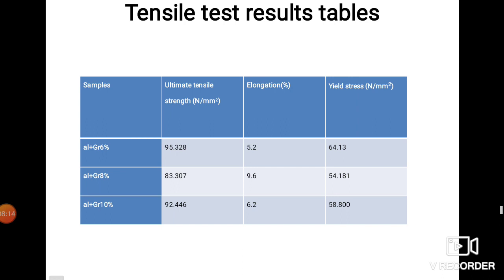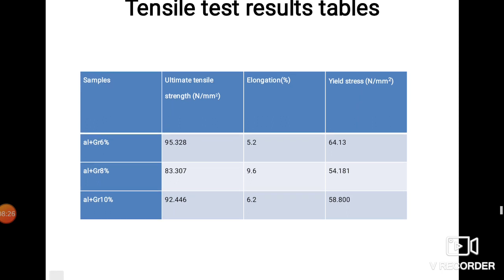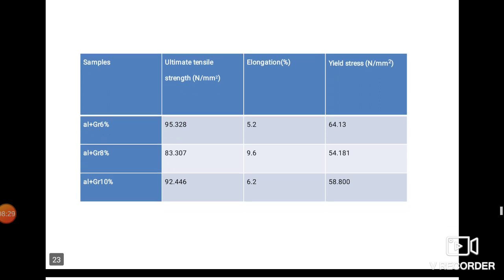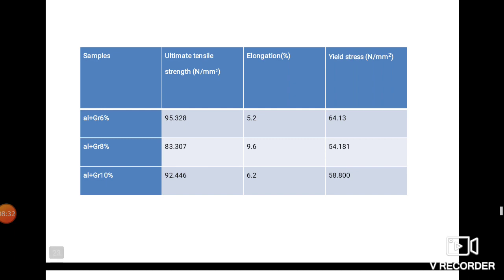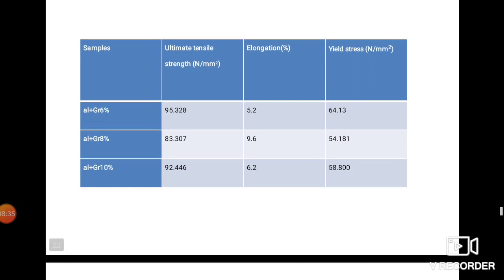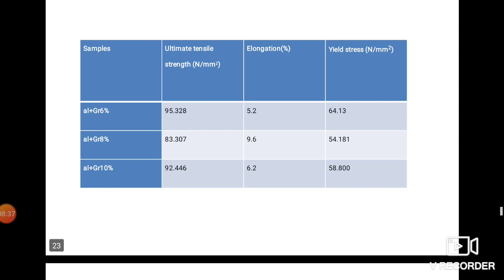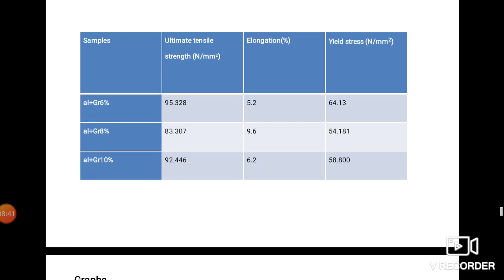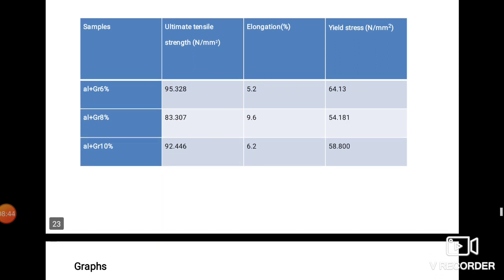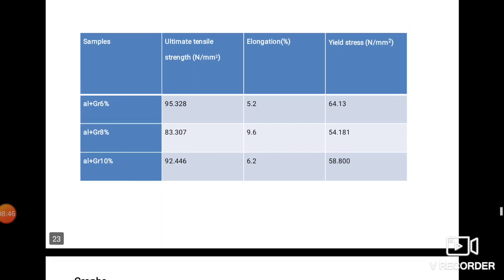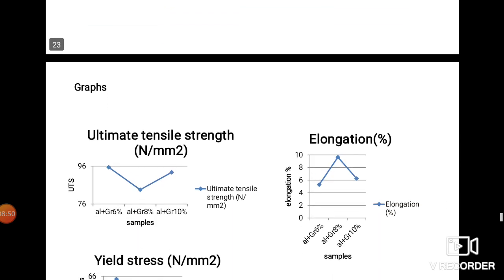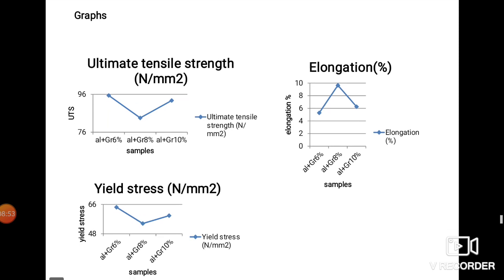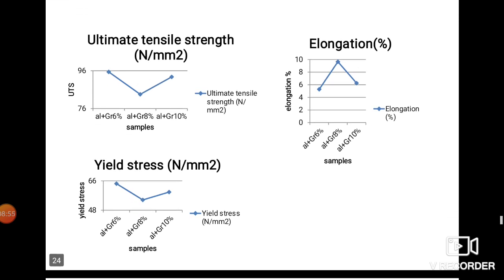With the 8%, the ultimate tensile strength decreased to 83.307 and the elongation increased to 9.6%, whereas the yield strength decreased to 54.181 Newton per mm square. In the case of 10%, the ultimate tensile strength increased to 92.446 to be exact. Elongation decreased to 6.2% and the yield strength was seen as 58.800 Newton per mm square. These are the graphs for the ultimate tensile strength. You can see the elongation and also the yield strength.